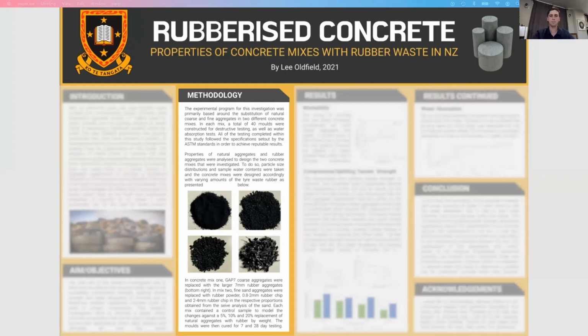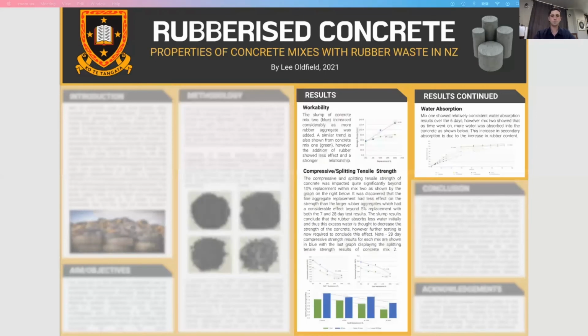These proportions were based on the particle size distributions obtained by the sieve analysis of the sand. Each mix was designed with a control sample, meaning there was no waste rubber present, and then a 5%, 10%, and 20% replacement of natural aggregate by weight, and these molds were then cured for 7 and 28-day testing.